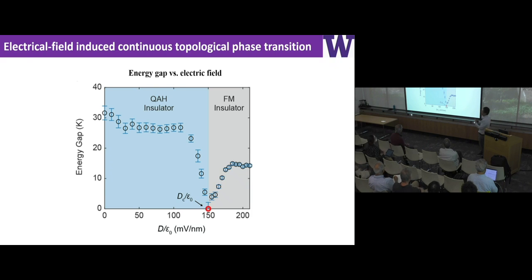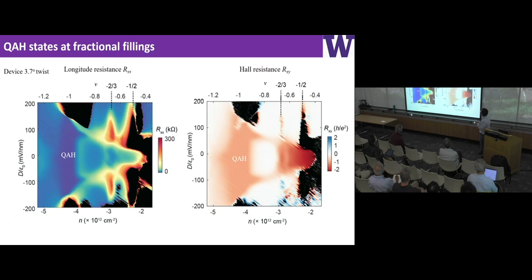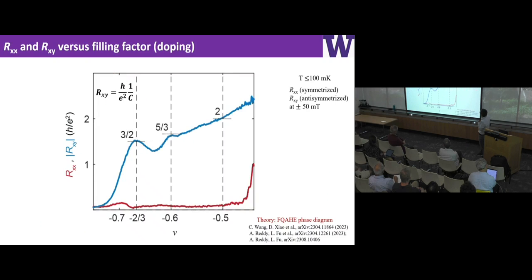So this shows you how we can use the electric field to tune the phase transition from one gapped phase, which is topological, to another phase, which is topologically trivial. And it's consistent with all the theory predictions you can think of, right? The gap must close. Okay, so now I'm going to shift gear to these fractional quantum anomalous Hall states. First, I want to show you the line cuts of Rxx and Rxy as a function of filling factor. And we see a few humps, corresponding to the fractional fillings 2/3 and 3/5, and this basically is a signature of the fractional quantum anomalous Hall state.